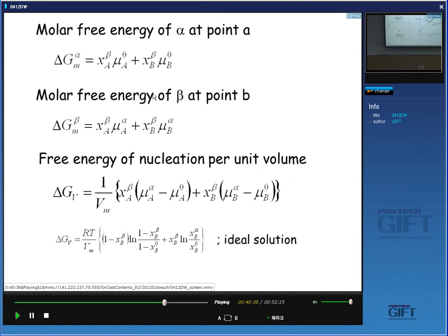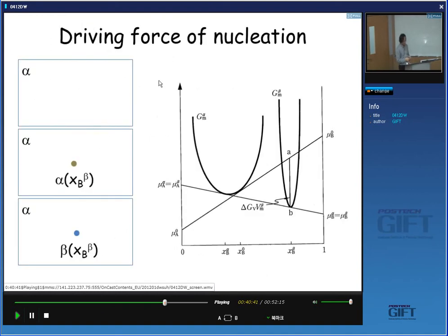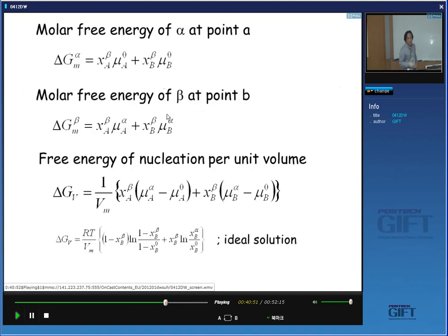And similarly, we can evaluate the molar free energy of beta at point B. Point B here, and the molar free energy is the linear combination of the chemical potential of these two values and composition. And you can write it down like this one. So the driving force for the nucleation of 1 mole of nucleus is the difference between these two values,